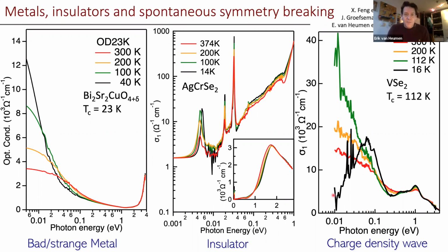And so the black curve very much resembles the response of the insulator, except with a much narrower gap. And if this was the only information you had, you might conclude that this material somehow becomes an insulator as well. And this makes sense. I mean, when you go into the charge density wave state, you open a gap at the Fermi level. And so you gap out excitations and essentially you get an insulator. Yet the reflectivity looks very different. And actually the reflectivity was very close to 1 below this energy range. So how come? Where does this come from?